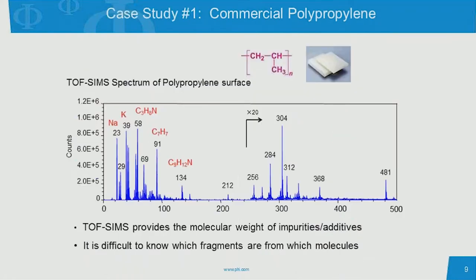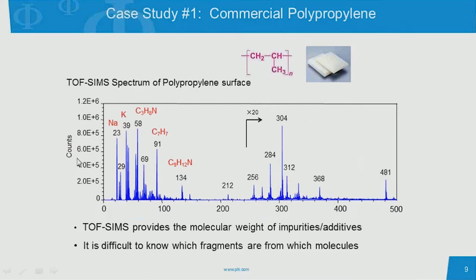This shows the TOF-SIMS spectrum of that same commercial polypropylene. In the low mass below 200 there's a bunch of fragments, and we see the impurities that XPS saw — sodium, potassium, small nitrogen-containing molecules. Above 200 and 250, we see the intact small molecule peaks, and the job is to identify each of those. The challenge is that this spectrum contains all the molecules and all the fragments together, so we don't really know which intact molecular ions produced which of the fragments.